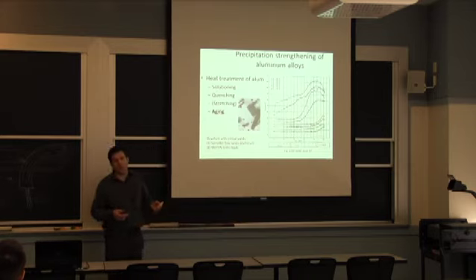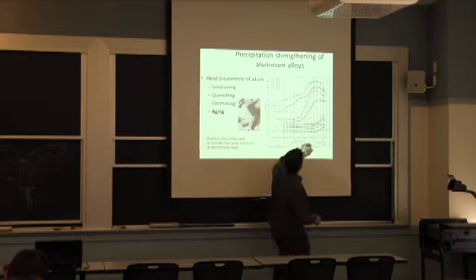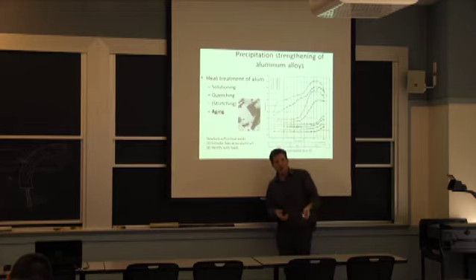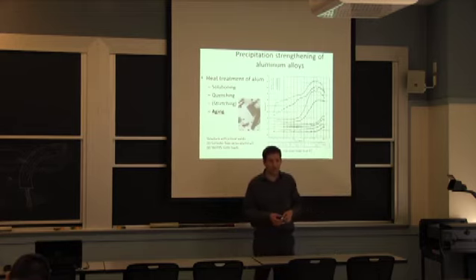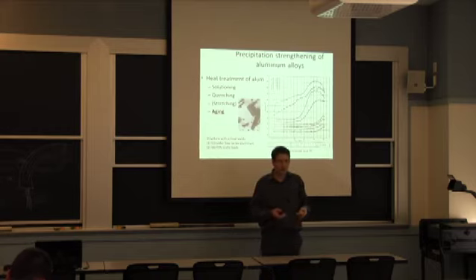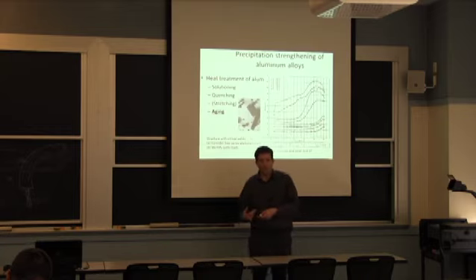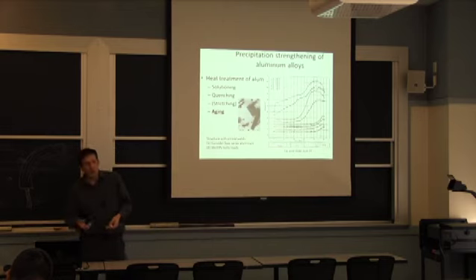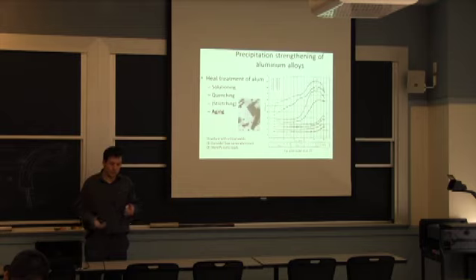Now, if you go to a T7 here, one of your advantages is that you can have bigger precipitates that are not going to interact as much in, say, stress corrosion cracking and other mechanisms. So there are reasons in terms of environmental resistance to go to an overage as opposed to an underage. The underage in general will give you more hardening, and therefore, if you're looking mostly for mechanical properties, you prefer to be slightly underage.